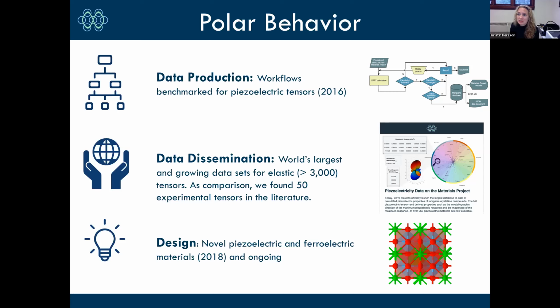I believe PZT has an exception in Europe from the banning of lead generally in industry because of its technological importance. So we again benchmarked the workflow for the piezoelectric tensor, and here the data was even more scarce. In the open literature, we only had 50 piezoelectric tensors measured to compare to before we decided that our workflow was good enough, because it was reproducing those piezoelectric tensors plus or minus 20% in this case. We have now calculated over 3,000, and they're again available in the Materials Project. And we set about to design a novel piezoelectric based on that data.